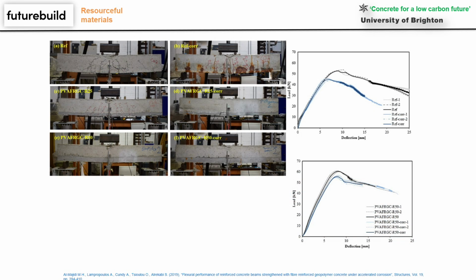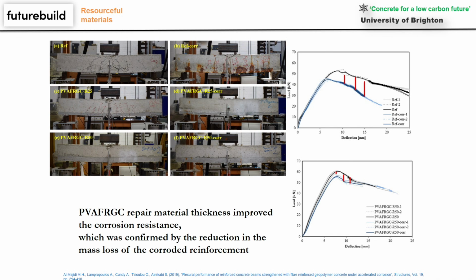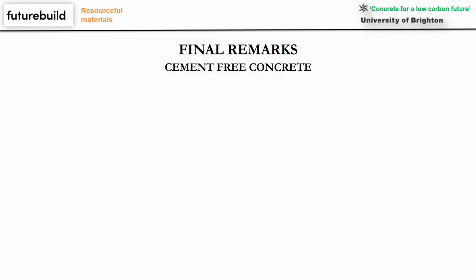And actually the findings were very good, so it was quite promising that the structural performance was significantly improved, but at the same time we did some accelerated corrosion tests, and we found that the geopolymer can also protect the steel bars from corrosion. So this can also lead to increased durability, which is very important for structural applications.